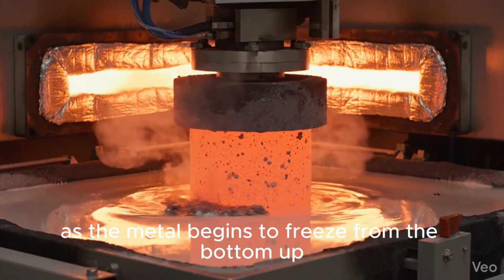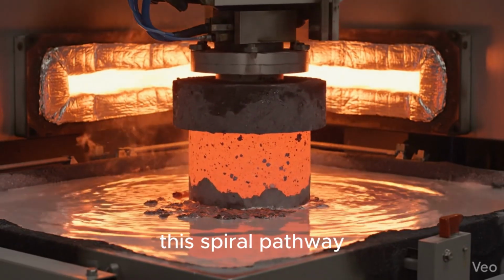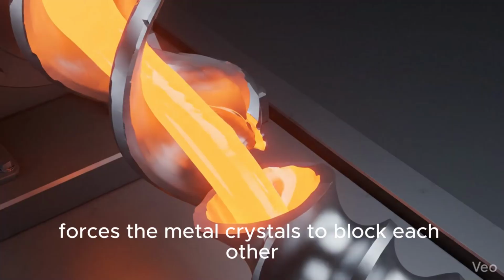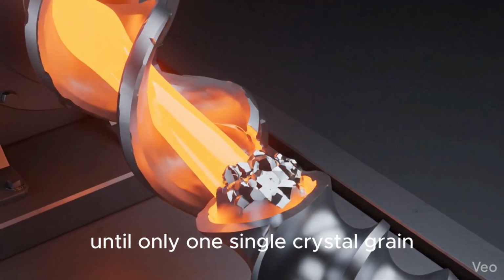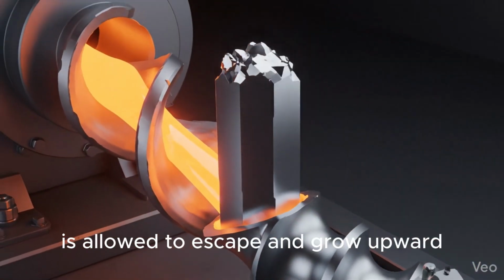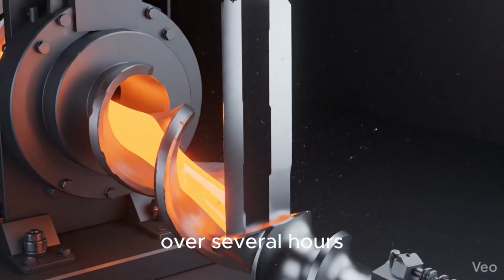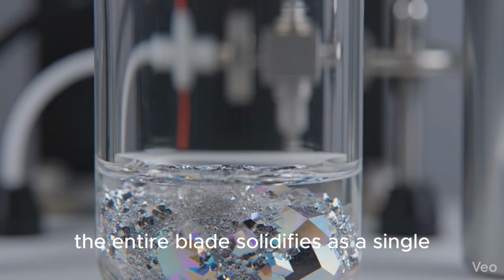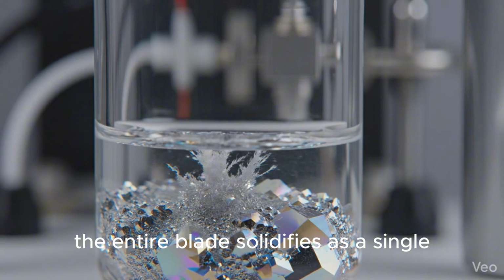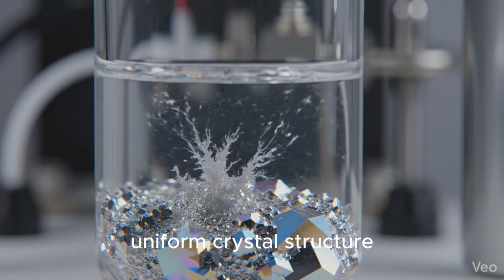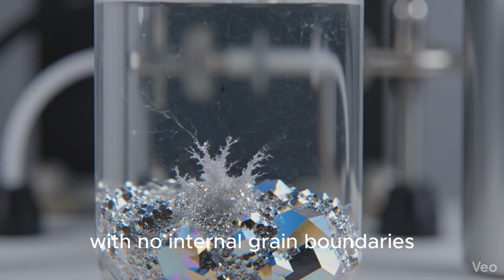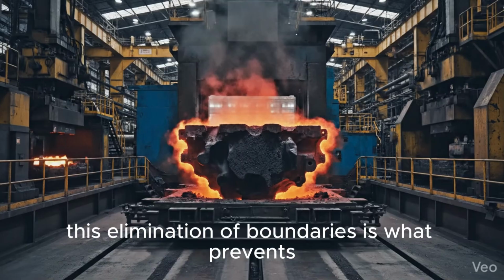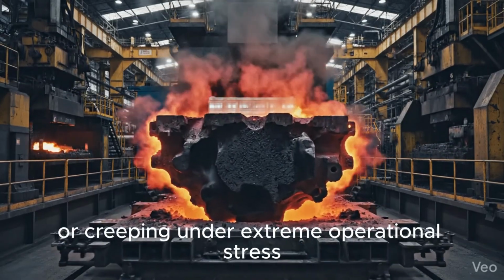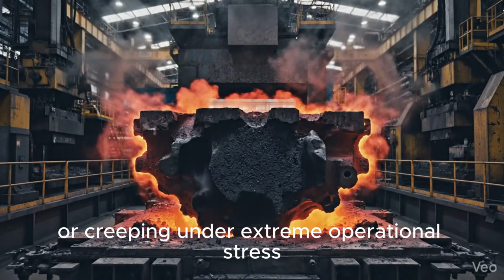As the metal begins to freeze from the bottom up, this spiral pathway forces the metal crystals to block each other until only one single crystal grain is allowed to escape and grow upward. Over several hours, the entire blade solidifies as a single, uniform crystal structure with no internal grain boundaries. This elimination of boundaries is what prevents the metal from stretching or creeping under extreme operational stress.